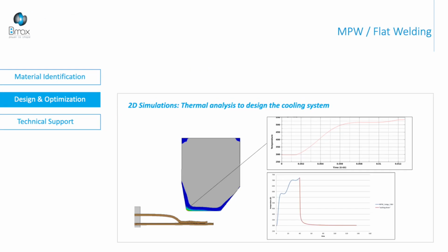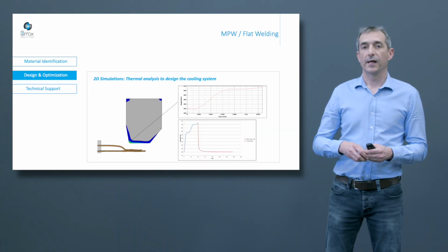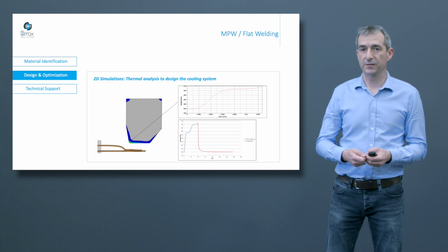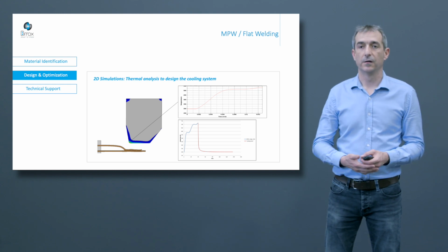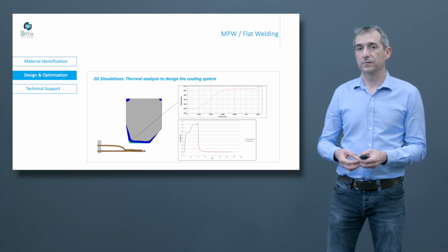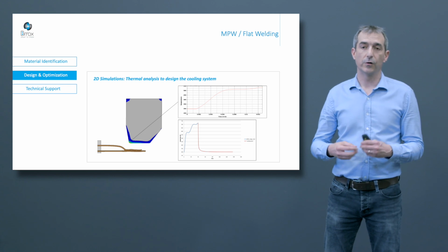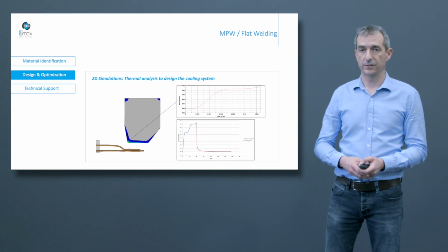After, thanks to these 2D simulations, we can calculate the temperature during the process. We can estimate the maximum temperature in the coil in the active zone, and we can compare it with the melting point. We don't want to melt the coil for sure. And for a lifetime analysis, we can estimate the temperature increase as a function of the production rate. And this data is used again to optimize the cooling system.